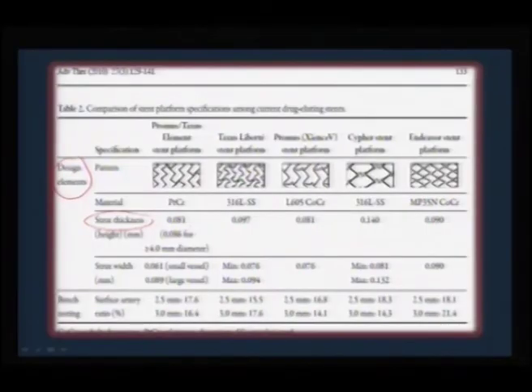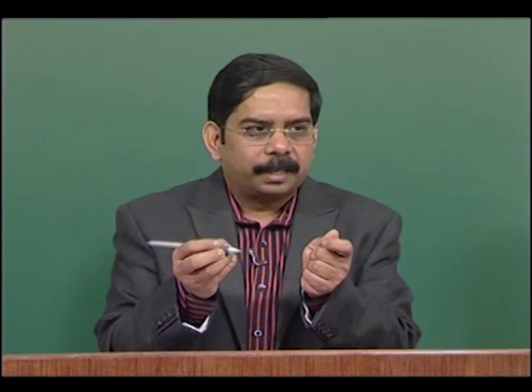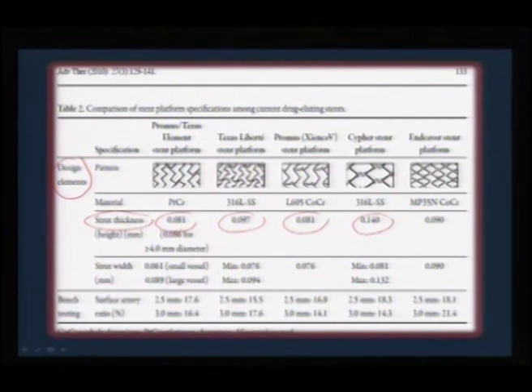So strut thickness is important, and if you carefully look at platinum chromium, look at cobalt chromium, and make a comparison with the stainless steel, you can clearly see that stainless steel ones are actually thicker, and it is not easy to bring down the strut thickness, because that is the property of this material. So in case of platinum, you can go down to 0.081 millimeters, which means you can make a very thin stent, and those are also easily deployable. So the different sort of alloys have the privilege of controlling the size. We will continue with the other information.